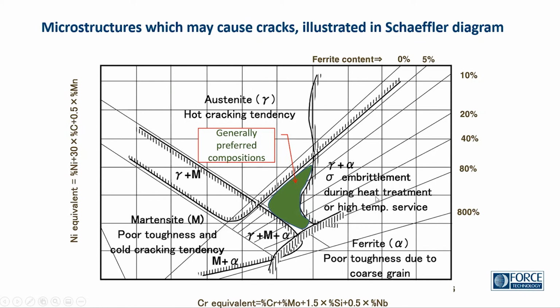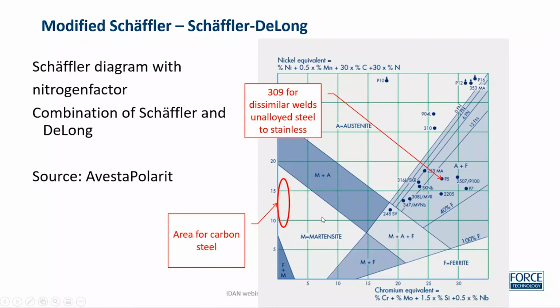And in this area, we have intermetallic phases forming. So it leaves us with this small area or window where we prefer to be when we weld stainless steel. And if we look into ordinary types of stainless steel, they would be in this area. And as an example, if you try to weld a stainless steel in this area with a carbon steel as the other part, a black and white weld,